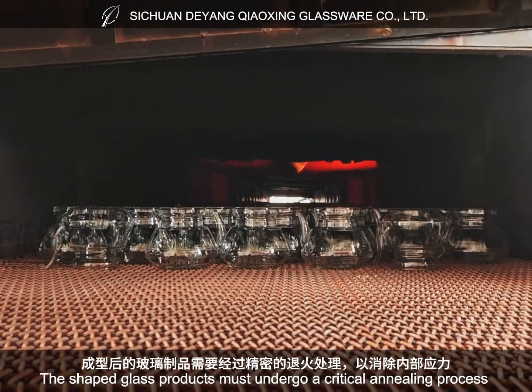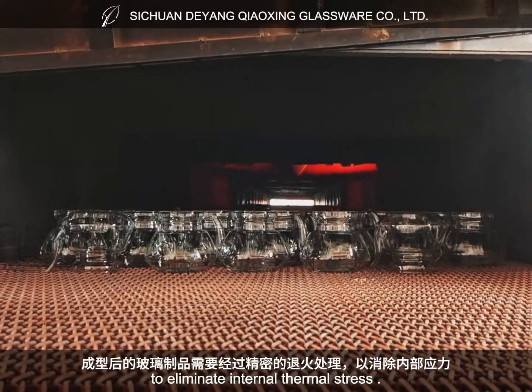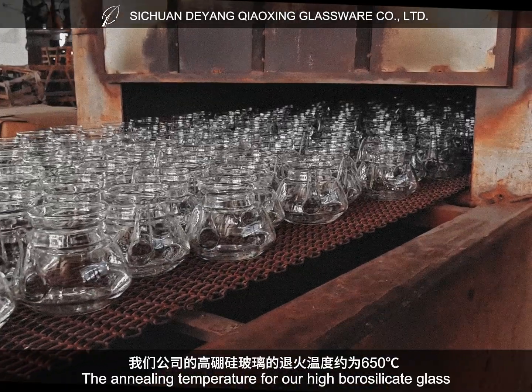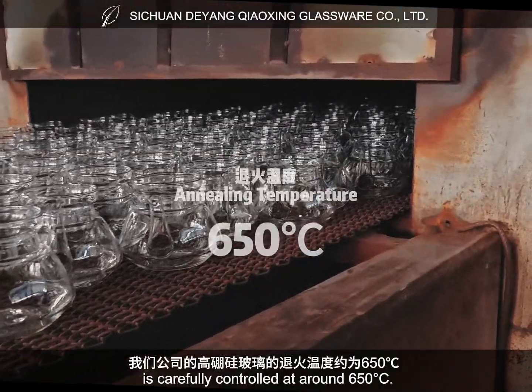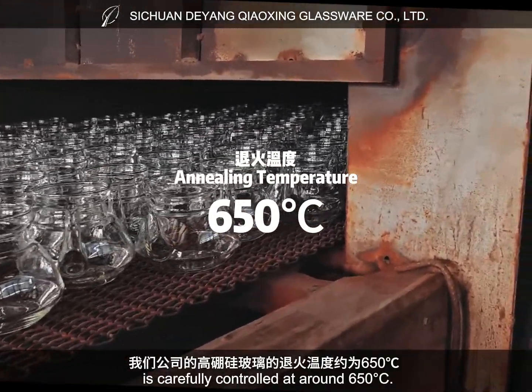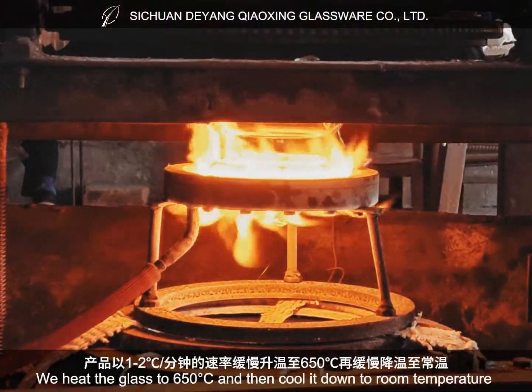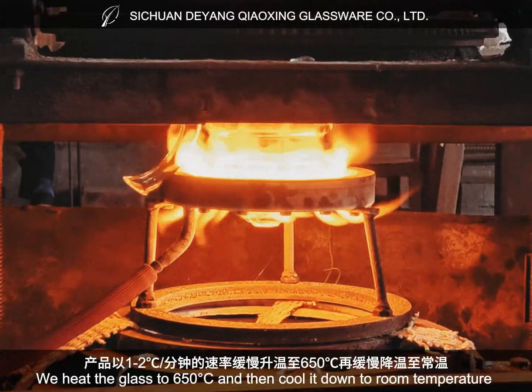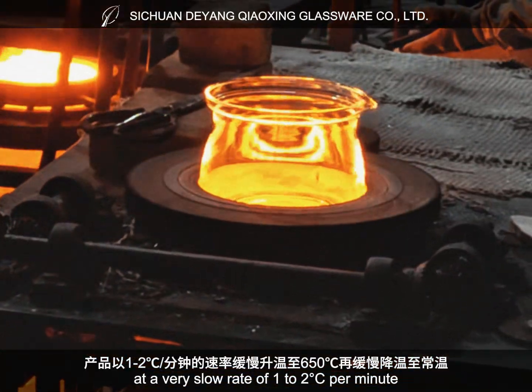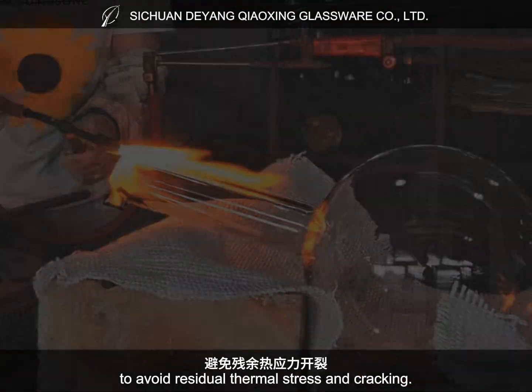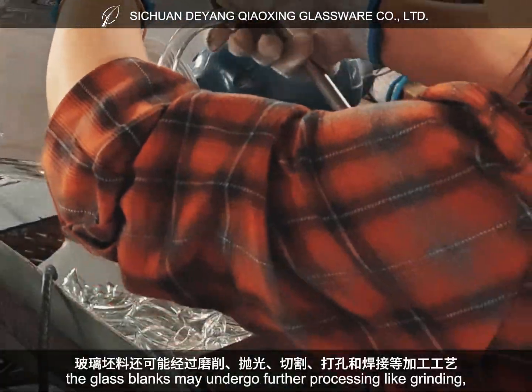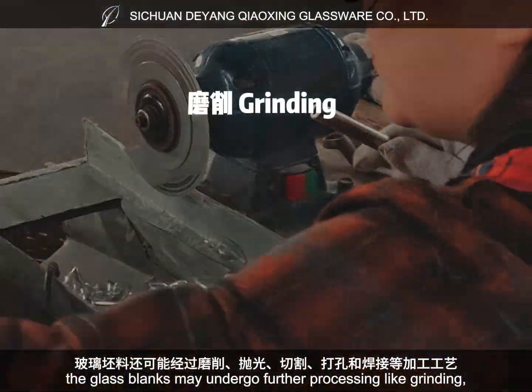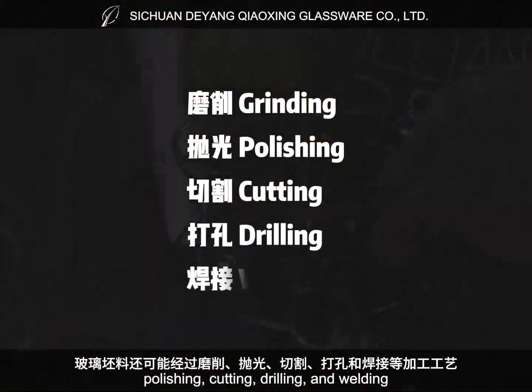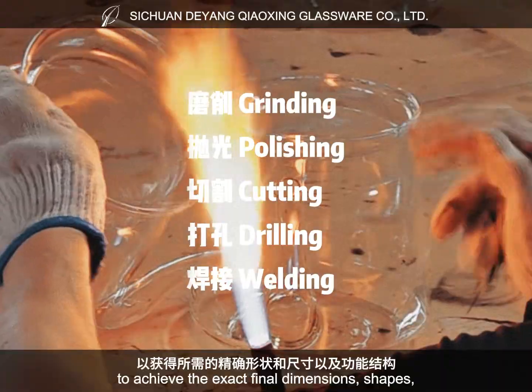The shaped glass products must undergo a critical annealing process to eliminate internal thermal stress. The annealing temperature for our high borosilicate glass is carefully controlled at around 650 degrees Celsius. We heat the glass to 650 degrees Celsius and then cool it down to room temperature at a very slow rate of 1 to 2 degrees Celsius per minute to avoid residual thermal stress and cracking. After annealing, the glass blanks may undergo further processing like grinding, polishing, cutting, drilling, and welding to achieve the exact final dimensions, shapes, and functional structures required.